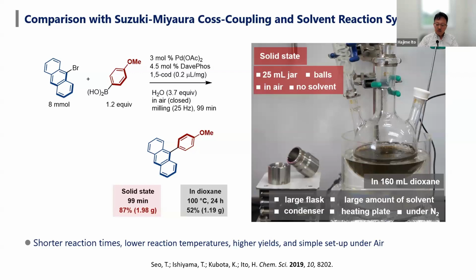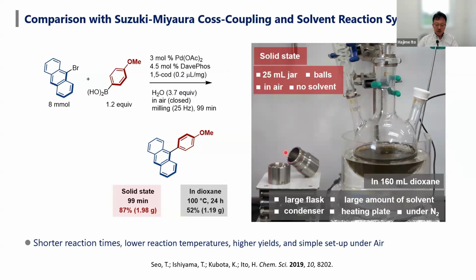But with our mechanochemical reaction conditions, we just use a jar. I'd like to show a pointer here - we just use this jar, and we just put a ball and substrate inside the jar under air conditions. We conducted this reaction at room temperature, and the reaction time is just 1.5 hours. Even with this reaction condition, we were able to get the desired product in very high yield compared to conventional reaction conditions. This slide clearly shows that our mechanochemical reaction conditions are much more efficient and much easier to do.